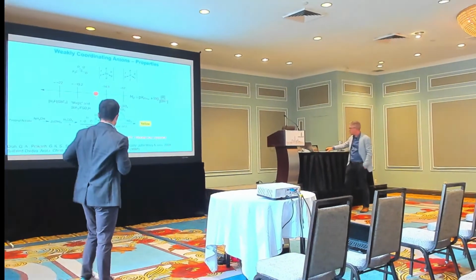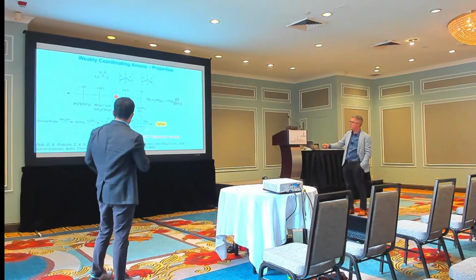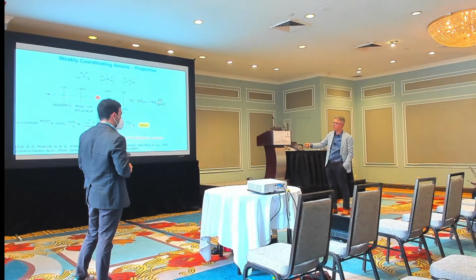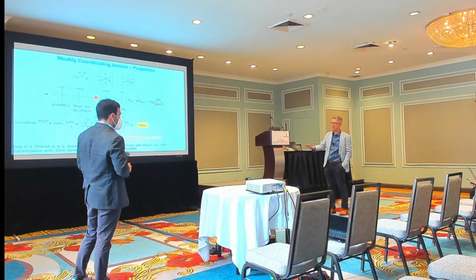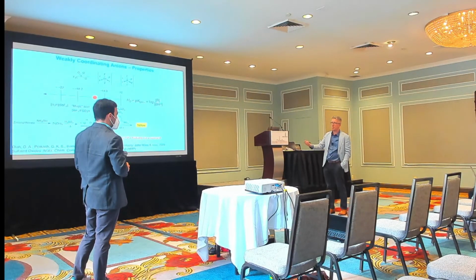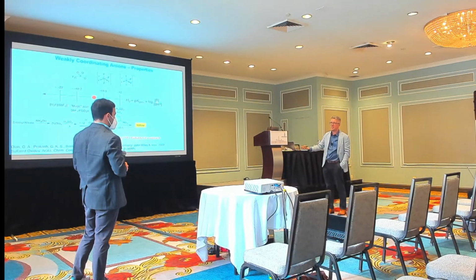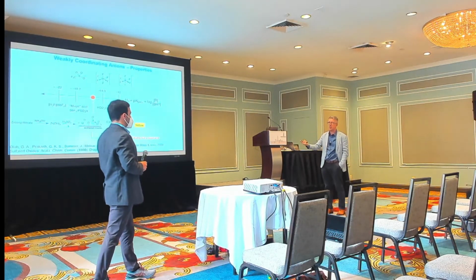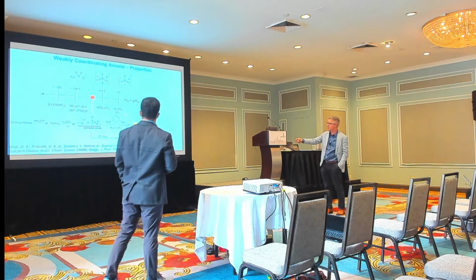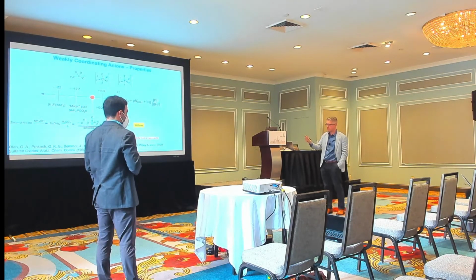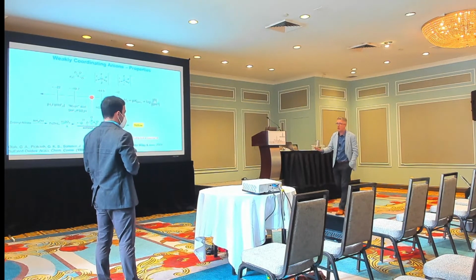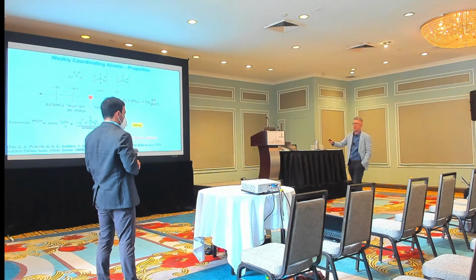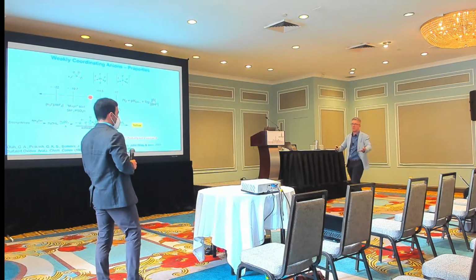So this was sort of the evidence, right? They took a variety of Hammett indicators and they soaked the solid material in the Hammett indicators and they just looked to see if it changed color. So these colorimetric probes for acidity have been kind of washed out of the community because they're just not, first, they're not characterized. There was no characterization that they accepted a proton. It was just literally turned yellow. Okay. And plus that they try to apply solution acidity methodologies to solid acids, and that's just flawed permanently.